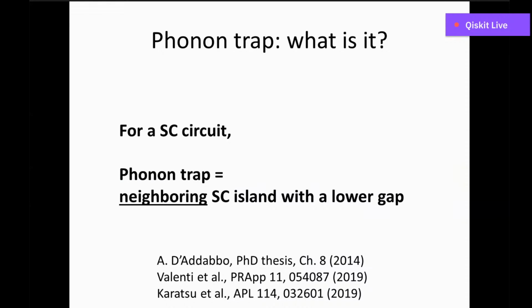How do we achieve phonon trapping? What is a phonon trap? If I have a superconducting circuit, what I call a phonon trap is a neighboring superconducting island with a lower gap. When I say neighboring, I mean this superconducting island is close to the circuit on the same substrate, but not in galvanic contact with it.